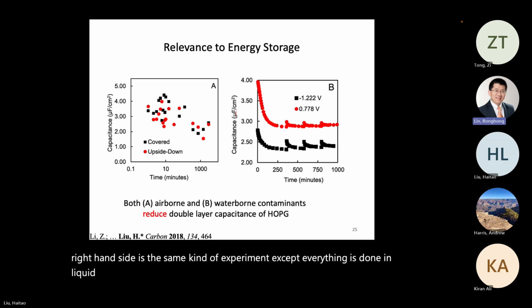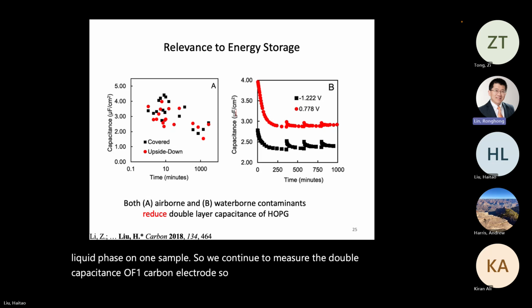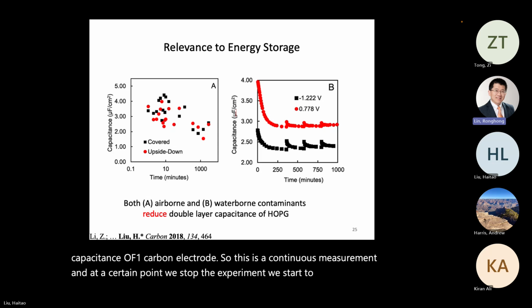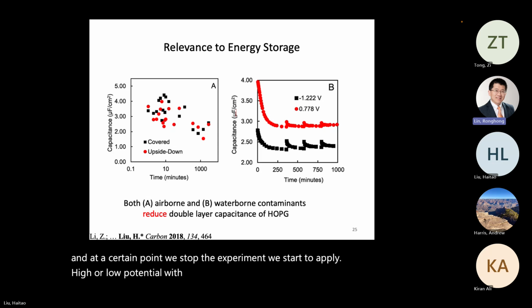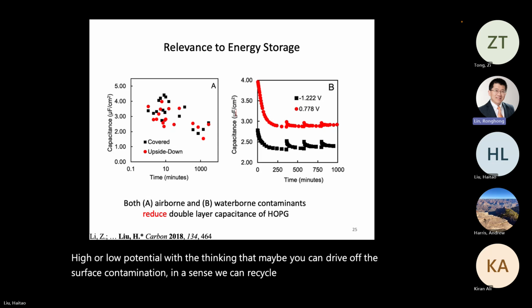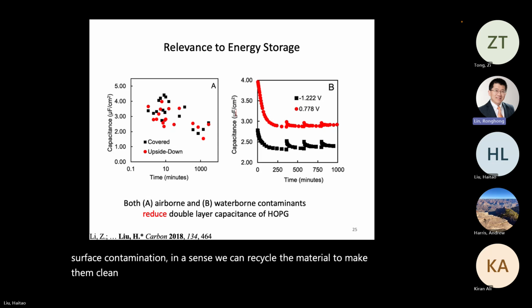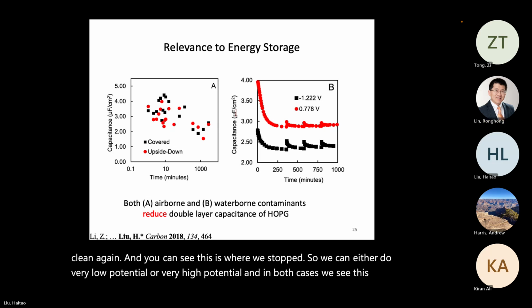On the right-hand side is the same kind of experiment, except everything is done in liquid phase on one sample. So we continuously measure the double layer capacitance of one carbon electrode. So this is a continuous measurement. And at a certain point, we stop the experiment. We start to apply a high or low potential with the thinking that maybe we can drive off the surface contamination. In a sense, can we recycle the material to make it clean again? And you can see this is where we stopped. So we can do either a very low potential or a very high potential. And in both cases, we see this temporary